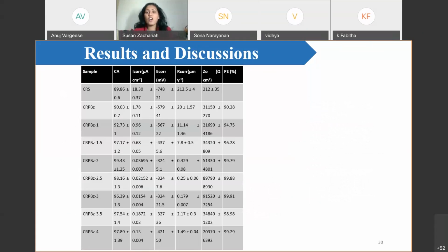I'm not discussing all the experiments we have done. I'm just going to discuss the main application, that is anti-corrosion. Here we have checked the protection efficiency of the coating. We found that even though the water contact angle was low, the electrical property of carbon nanotube (CNT) made the coating a good protection for the CRS.